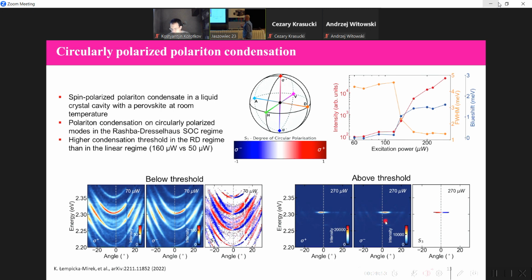Now if we make a map of degree of circular polarization, you can see that there is some splitting between circularly polarized condensates. So this is the condensation in the Rashba-Dresselhaus regime.